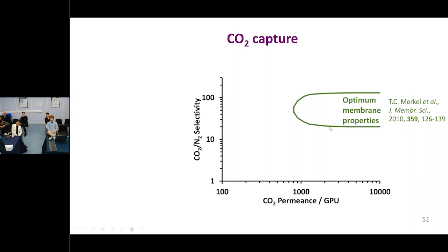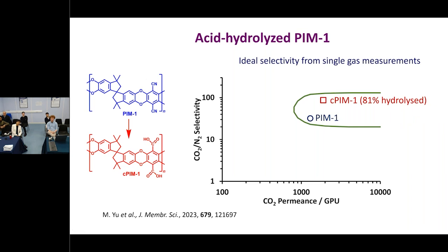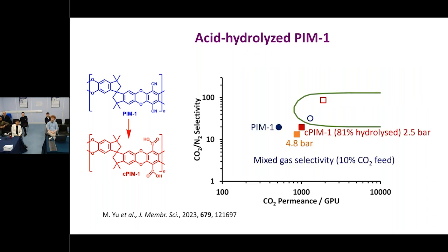And just to illustrate some of the other things we have to think about, we can do an acid hydrolysis into a carboxylate-rich polymer, which seems to perform really, really well if we look at single gas permeation. But this is a thin film, and this is where plasticization can start to come. It doesn't look too bad on a thick film. It starts being really serious on a thin film, particularly with things that have hydrogen bonding. And that's a large part of what's going on. And so when you go to mixed gas, it's still actually quite good performance, but drops out of the range we're really looking for. And that's a plasticization effect. And so again, that's something that we're looking at, finding ways to improve on that. We can know what's possible, but we still have to play around to get the performance that we're looking for.